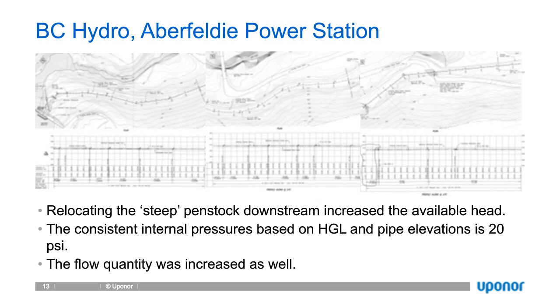The project was relocating the penstock, the steep portion of the penstock leading to the turbines downstream, and of course accumulating additional head as we did so. So there's a fairly consistent internal pressure, which is based on the difference between the hydraulic grade line and the elevation of the pipe, and it's about 20 psi for the entire project length.